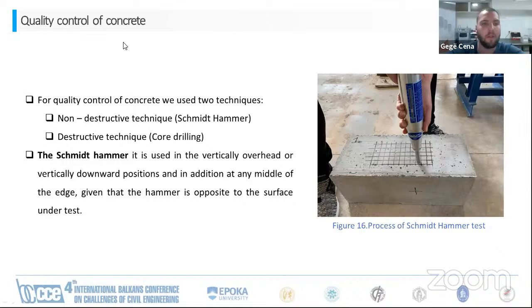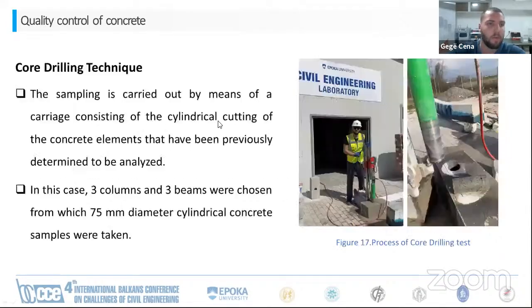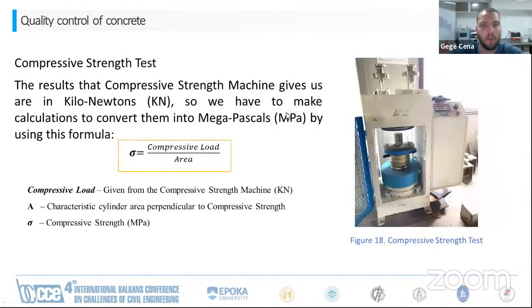Quality control of concrete. We also made the quality control of concrete by two techniques. The first technique was a non-destructive technique with the Schmidt hammer, and the second technique was a destructive technique with core drilling. The core drilling technique is carried out by means of a carriage consisting of a cylindrical cutting tool, cutting the concrete elements that have been previously determined to be analyzed. In this case, 3 columns and 3 beams were chosen, from which 75 millimeter diameter cylindrical concrete samples were taken. We also tested the compressive strength of those samples, and